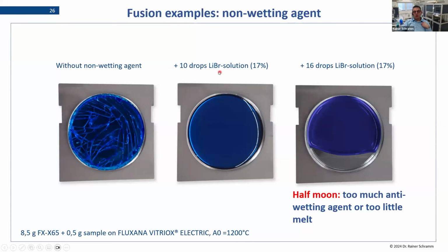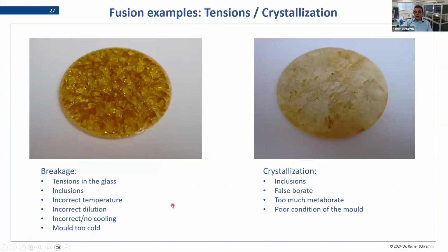Yeah, when we add then bromide, it is stable and will release very easily. But here I also want to show you if it's overdosed. That means if we have too much bromide, we get this half moon effect, and then you have either to reduce the non-wetting agents, or you have to add more material. So that means you increase flux and sample to fill again the complete mold. So here, two examples, full crystallization, and this here is still glass, but so much tension that it breaks.